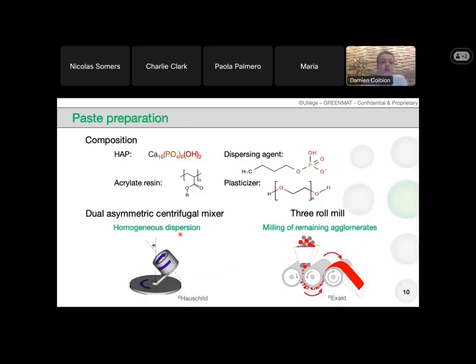So the next step is the preparation of the paste. We have mainly 4 components inside the paste. The first one is the recovered hydroxyapatite, and the other main component is the resin. We are using an acrylate resin. And as I said before, there is quite an incompatibility between the hydrophilic hydroxyapatite and the hydrophobic resin. So we have to use a dispersing agent, which is in our case phosphate esters. And we are also adding a plasticizer, which is a type of polyethylene glycol. To disperse and have a homogeneous dispersion, we are using a dual asymmetric centrifugal mixer. And after that, we put the mixture in the 3-roll mill in order to mill the remaining agglomerates and recover a smooth paste.